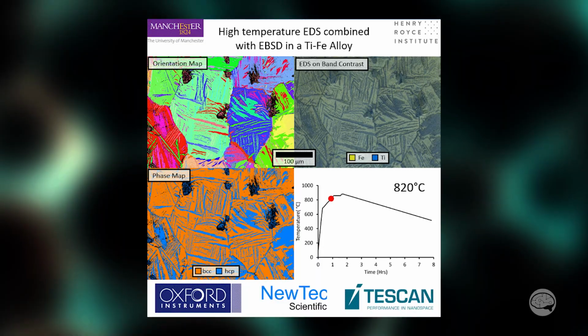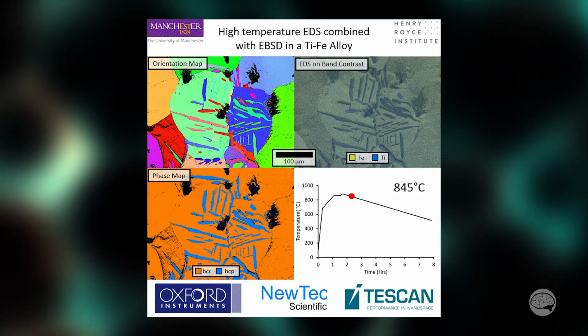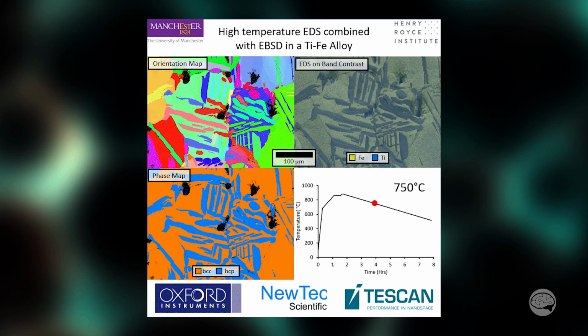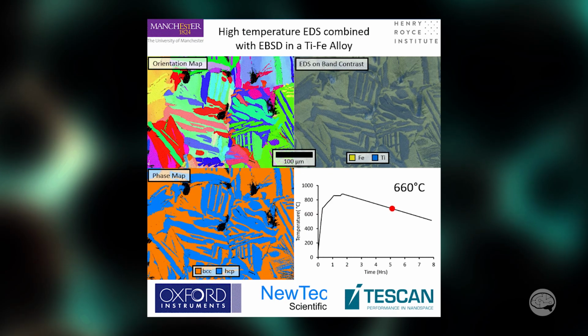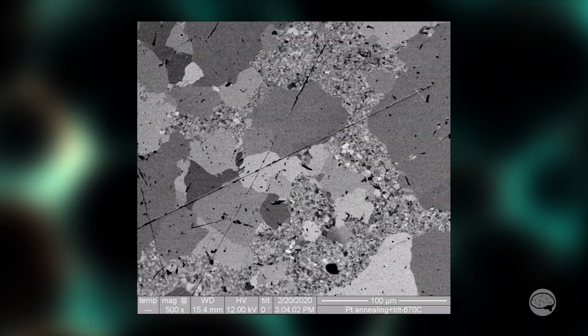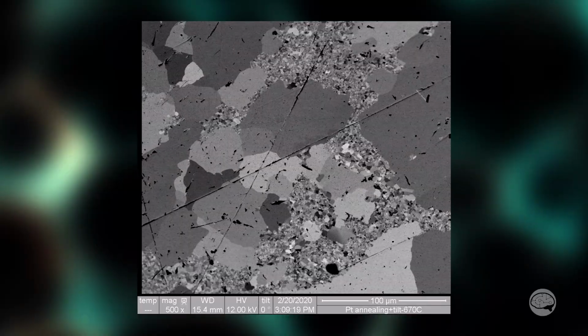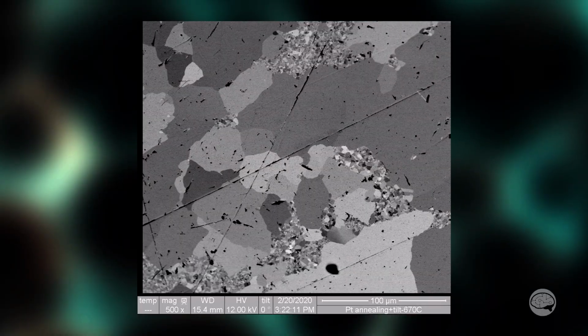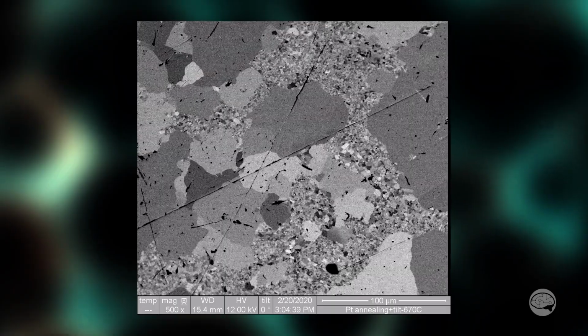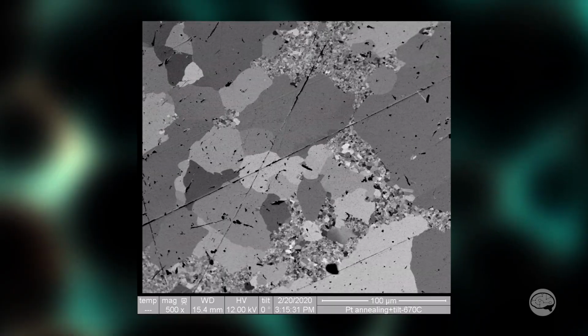So there are a lot of in-situ tensile or heating holders on the market. What makes yours special? Why would someone be really interested in yours? First, because the way that we heat up the sample is very specific. We just heat the sample. That is why we can go inside SEMs for hours. We have done tests at 850 degrees C during 24 hours inside the SEM, and the pole pieces just heat up about 3 degrees C. That means you do not destroy your SEM because you don't warm up the inside.